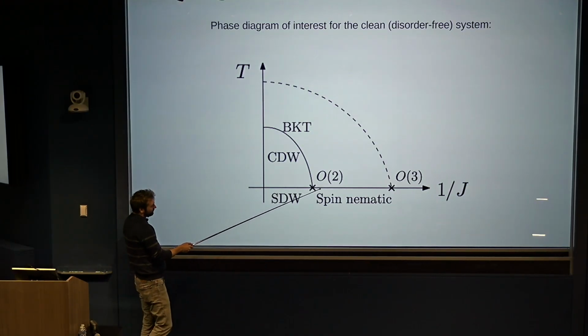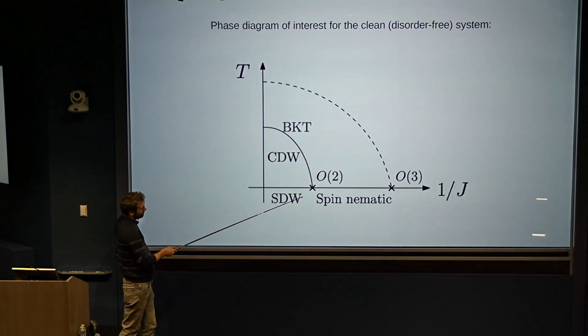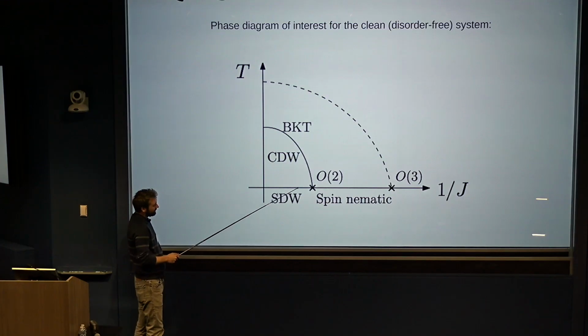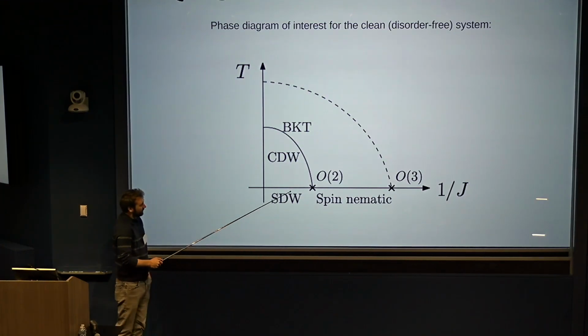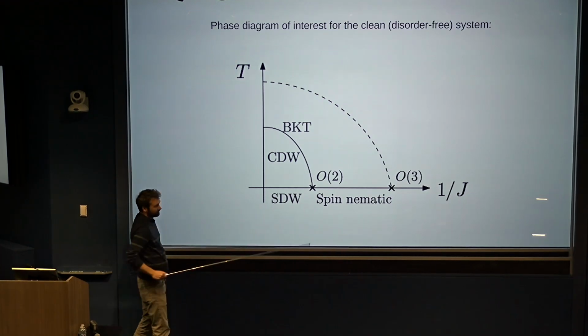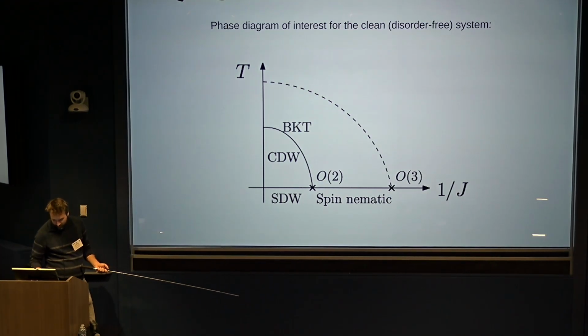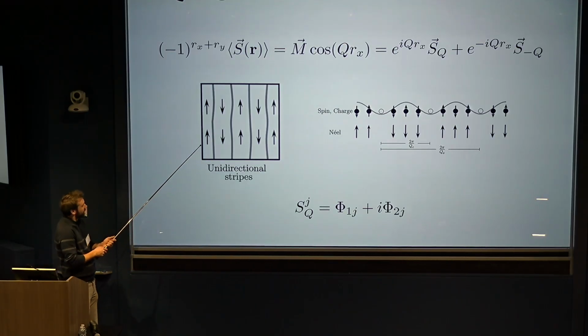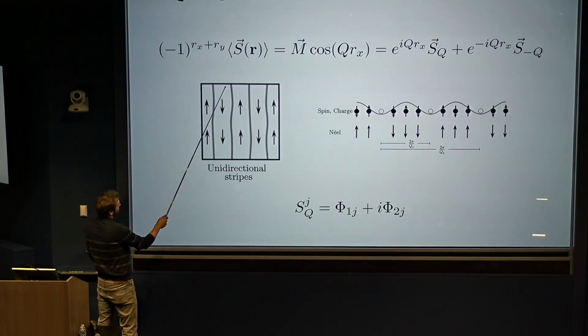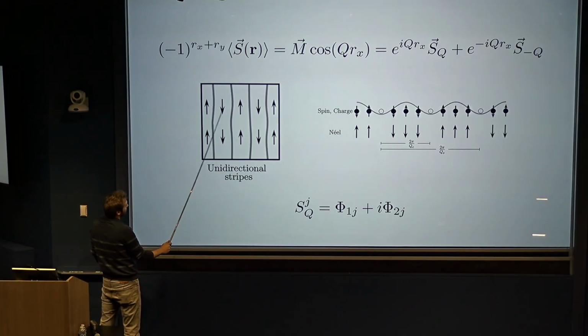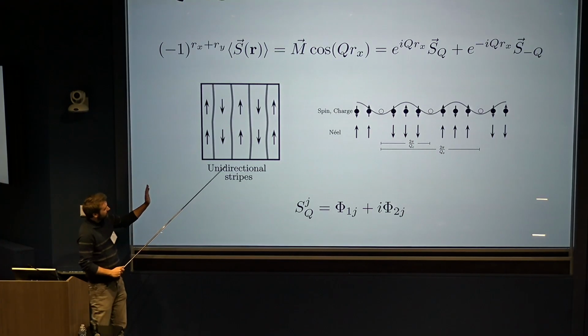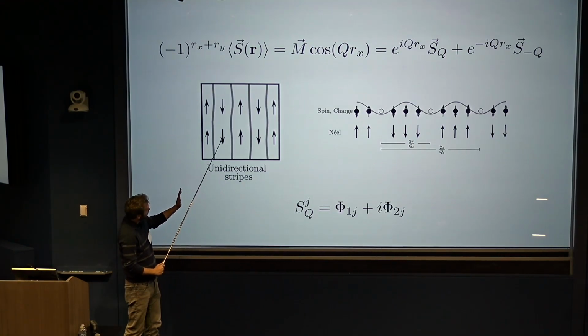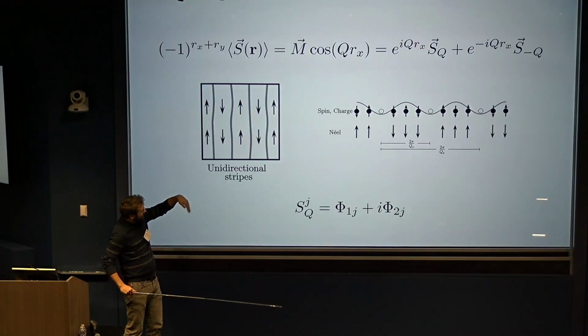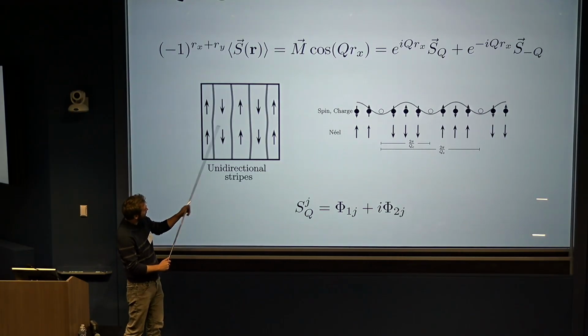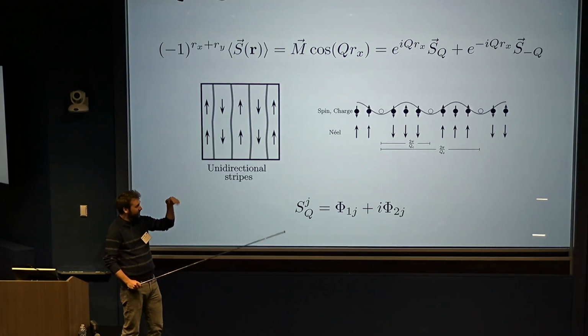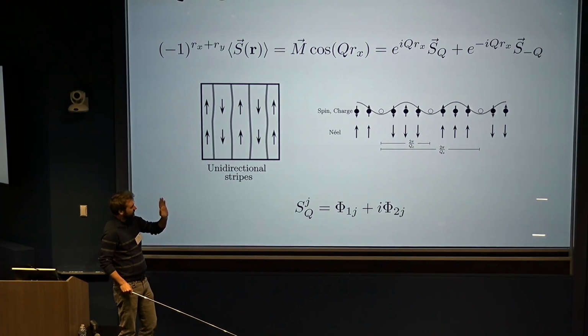Then as you decrease the stiffness, first the charge degrees of freedom disorder. But when this happens, you actually don't go to a completely symmetric state. You actually go to what is called a spin-nematic state. That's because, if you look at this picture, charge fluctuations, so the phason fluctuations, you should imagine that these domain walls here, these gray lines, start fluctuating. And so whenever this gray line passes through the spins, through the antiferromagnetic order, they change direction. So when these gray lines, the charge order, start fluctuating, the direction of the spins unavoidably also starts fluctuating.